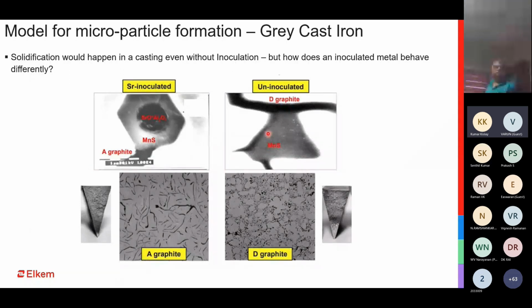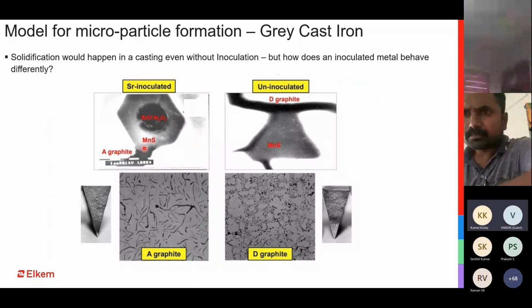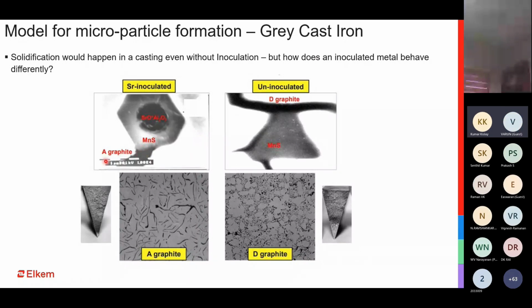If you look at the photograph on the left, it's a gray iron. I mean, you can see it from the microstructure which is shown below. It's a gray iron casting where you have a core which is combined of strontium oxide, aluminum oxide, and then you have the manganese sulfide shell on the outside, and it is hexagonal in shape. If you look at it, it has 6 sides, so it's basically hexagonal in shape. And this is the site on which the carbon which was being thrown out from the iron matrix would precipitate as a graphite.